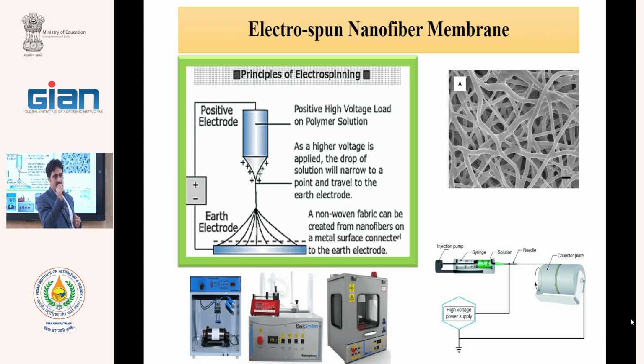In the preparation of polymeric solution, not all polymers completely dissolve. Some of them do not dissolve well and form gels. The gel is a particle. And these gels that we cannot see in the solution can block the needles, nanometric needles.